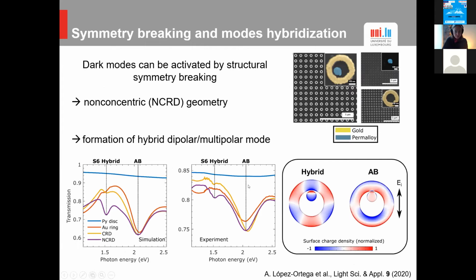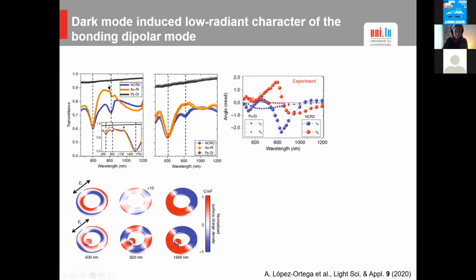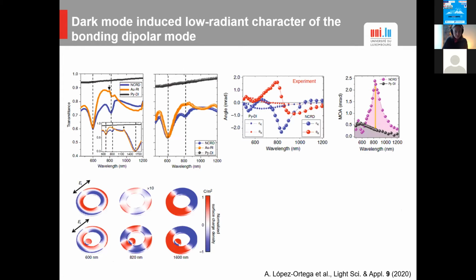But here, the take-home message is very important, because here what we showed is that at that specific wavelength, the magneto-optical response is one order of magnitude larger than the one you can achieve with the excitation of a simple dipolar mode. And this was a fundamental limitation before, because usually people rely on the excitation of localized plasmon based on dipolar oscillations, okay?